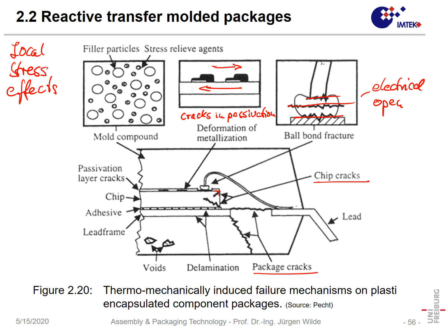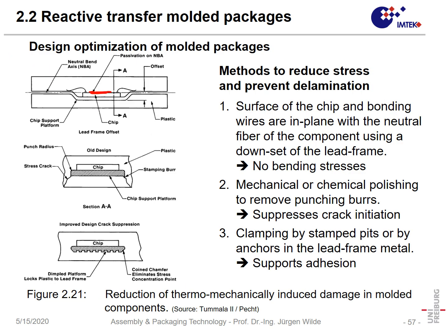One thing we can do is have some rubber-like particles in the molding compound, so the stress concentrations near the edges and corners are not so bad. There are other tricks we can see. First of all, I said these sharp edges, we have a so-called stamping burr. So that's like a knife. So if you have stamped something and you touch it, you can even cut your finger. It is so sharp. And that burr can be removed by some grinding. And so we get rounder edges here. That is one thing which is important. So we avoid these cracks on the stamping burr.